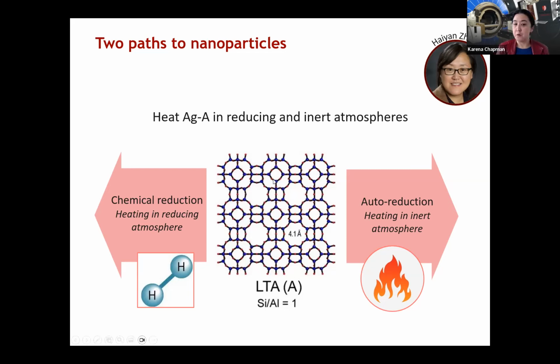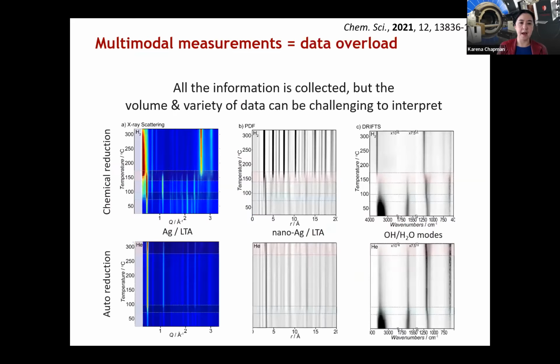So forming silver on our LTA zeolite, there are two routes. We can either reduce it chemically under hydrogen gas flow, or we can just heat it and it undergoes an auto reduction. So two different reactive steps that we explored, and we can collect X-ray scattering data for each route, and the complementary PDF that we derive from that X-ray scattering data.